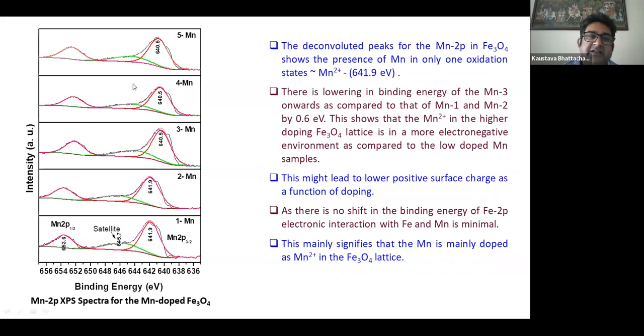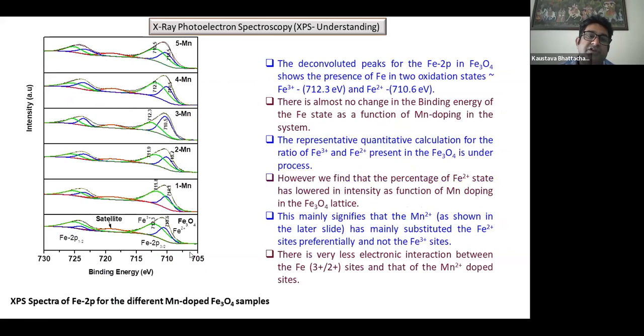Similarly, if we check the XP spectra for the manganese, what we get is that the manganese has only a single oxidation state. Manganese is present as Mn+2 only. Manganese doesn't have any other oxidation state. And this Mn+2, if we check from the previous one, is replacing the iron +2 in the process of doping.